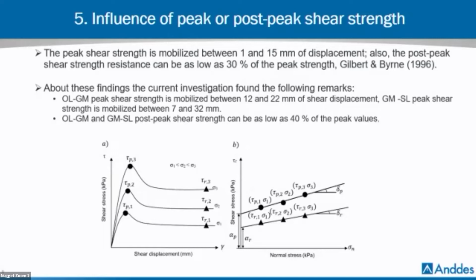However, this criterion can be very conservative to estimate the factor of safety in a specific situation, such as a static condition, for example. The influence of the shear strength was studied by other authors such as Gilbert, who indicate that the peak shear strength is mobilized between 1 to 15 millimeters of displacement in large scale shear tests.